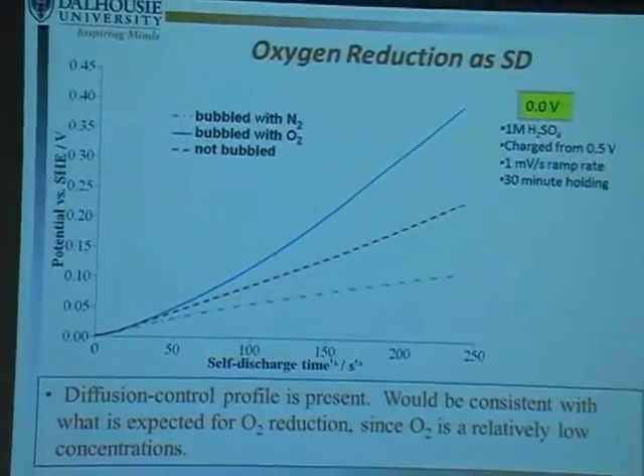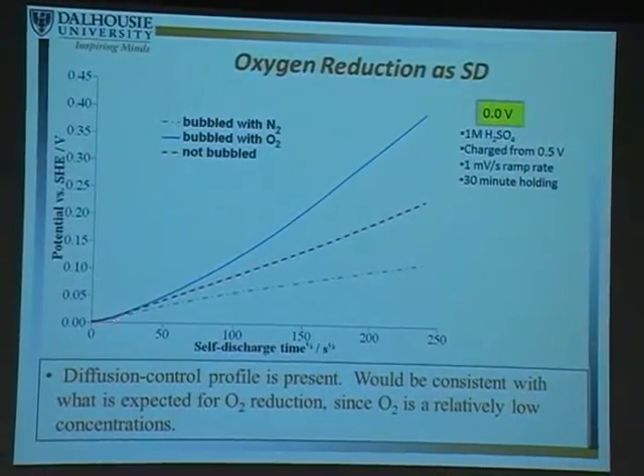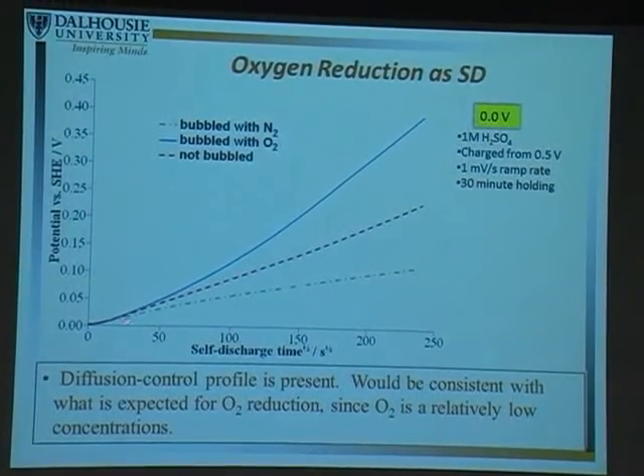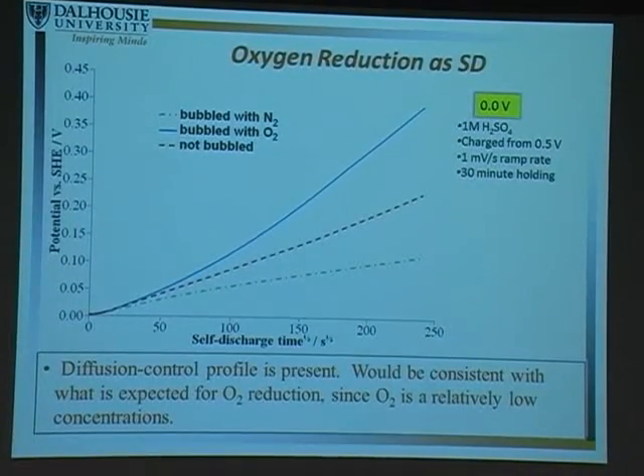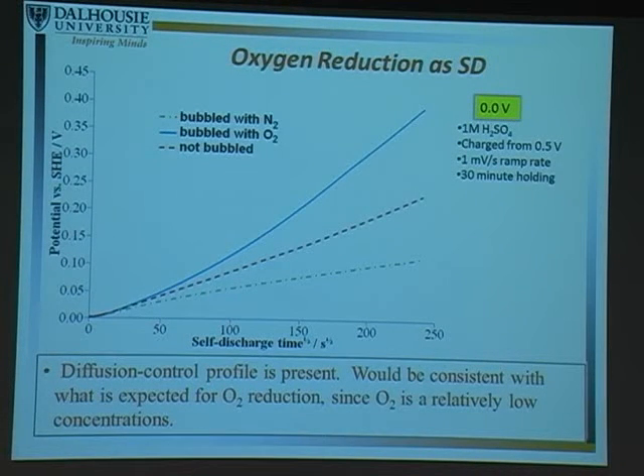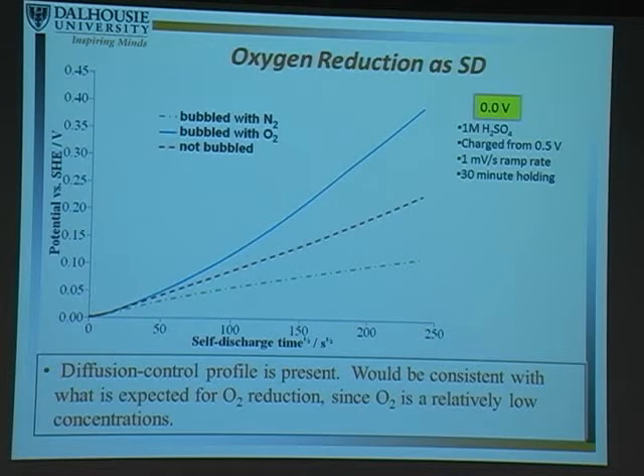And when we plot in different ways, we see that we have a relatively linear plot when we bubble with nitrogen. It's relatively linear when we don't bubble, when we plot it versus square root of time, absolutely consistent with diffusion of oxygen being the key component here. As we increase the oxygen concentration, it moves away from a diffusion controlled process. So we are identifying oxygen as the main cause of self-discharge for the negative electrode, which of course is going to be a problem in commercial systems because removing all of the oxygen is difficult. And in fact, for porous electrodes, it's particularly difficult.